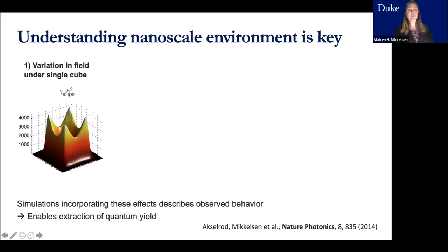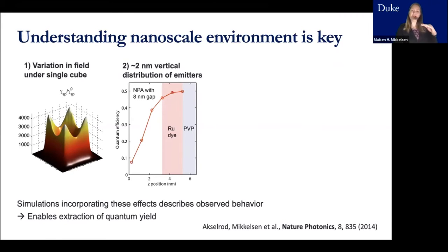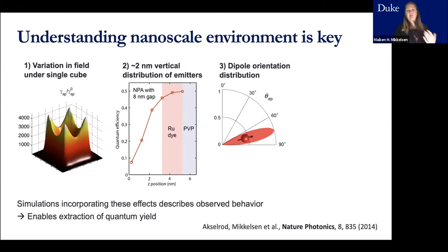We don't just need single nanometer precision, but we also need to carefully understand other things going on. One thing we had to understand is the variation of the field under a single cube. In this case, we're looking at an example of molecules, so we are basically averaging over all these different positions. This is COMSOL simulations showing the variation in the spontaneous emission rate. We also had to understand exactly where these dyes are located, because the closer to the middle they are, the more the non-radiative rates are modified, and the dipole orientation.